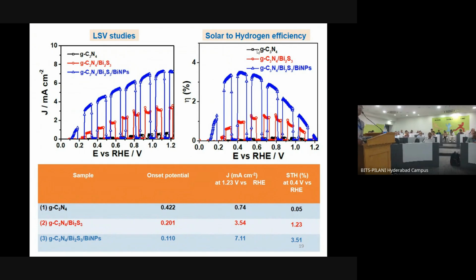C3N4, though many times you see good reports about C3N4, especially in these conditions, the current is in milliamps. Then you look at this one, and the moment you put bismuth based nanoparticles, your currents are improved, and so is the STH conversion, the solar to hydrogen conversion.